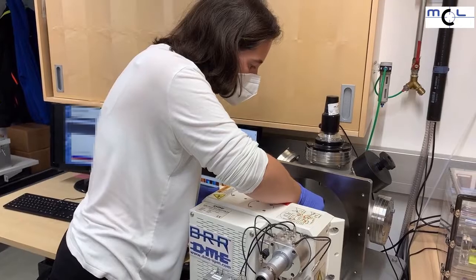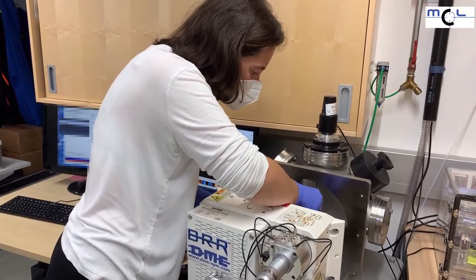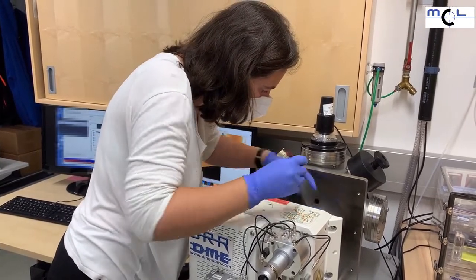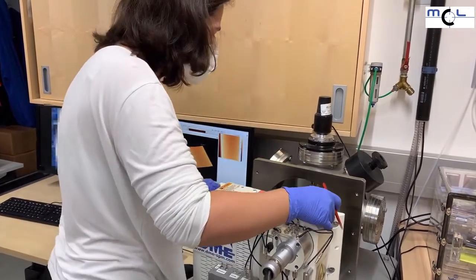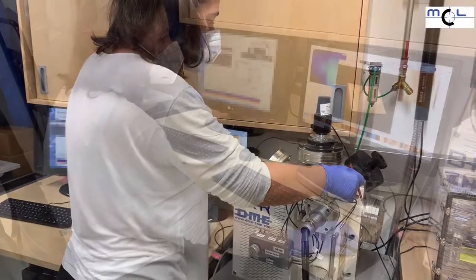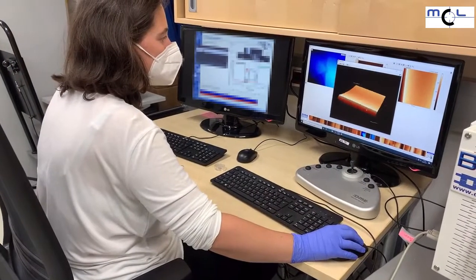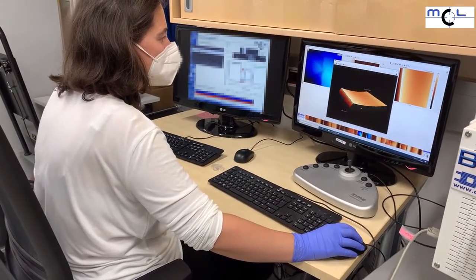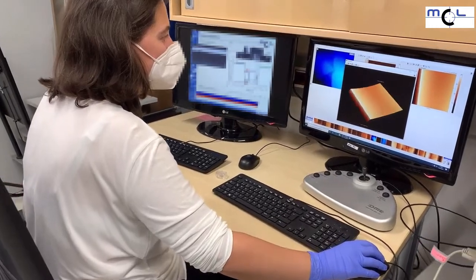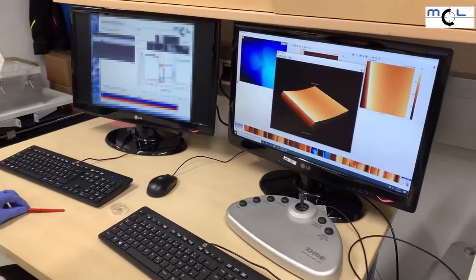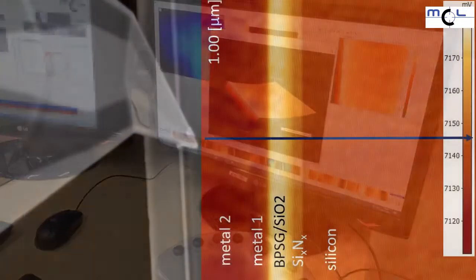With the scanning thermal microscopy, it is possible to map the thermal conductivities with a high resolution down to 50 nanometers. By scanning over the cross-section of the high-power device, an image of the thermal conductivities of the layer stack was generated.